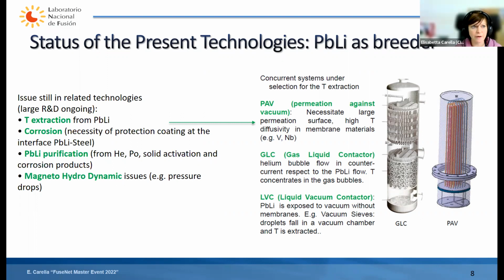We do not have a candidate yet, but we are still studying extraction systems based on different physical processes. In one case, we have permeation against vacuum. In the other case, we use a gas-liquid contactor. And in the last case, we have a liquid-vacuum contactor. Then we have to solve the big problem of corrosion, because lithium is highly corrosive, and we have lead lithium moving in all the channels in the form of liquid metal.